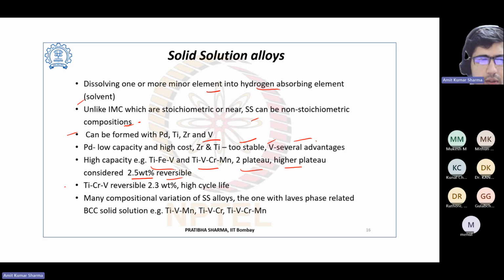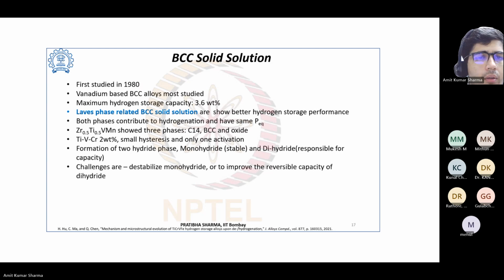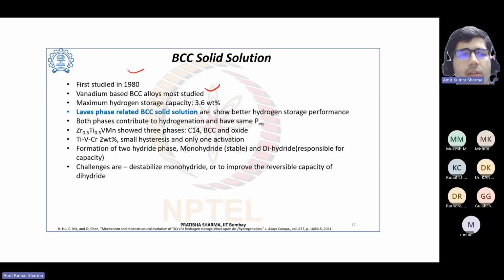This kind of composition can also have a high cycle life. There are many compositional variations of SS alloys, the ones with Laves phase related. The BCC solid solutions are examples like TiVMn, TiVCr, TiVCrMn. These are examples of BCC solid solution. This was first studied in 1980. Vanadium based BCC alloys are the most studied. In these alloys, we can have a maximum hydrogen storage capacity of 3.6 wt%. Laves phase related BCC solid solutions have shown better hydrogen storage performance.